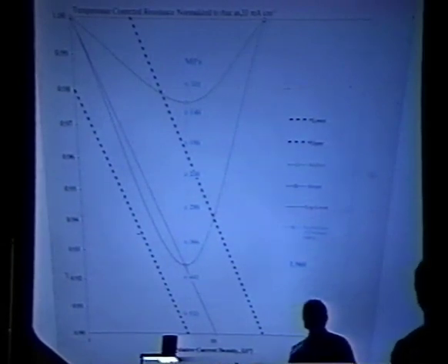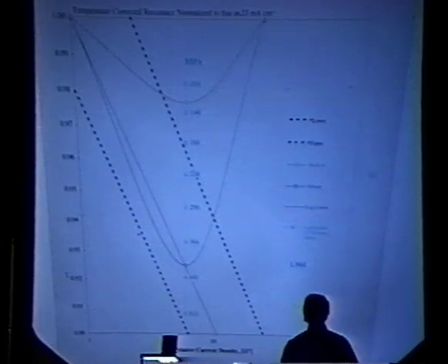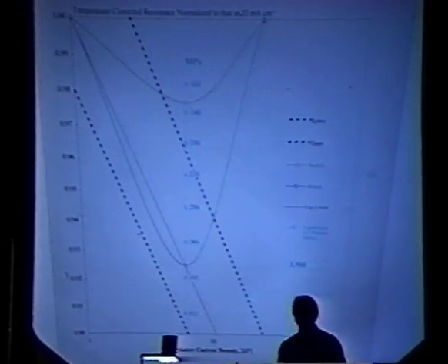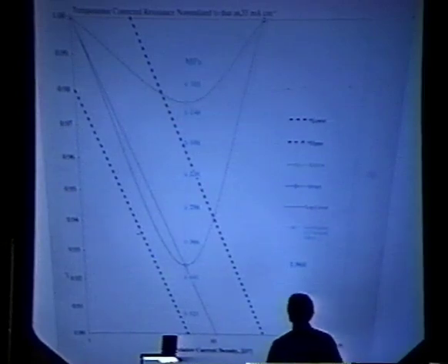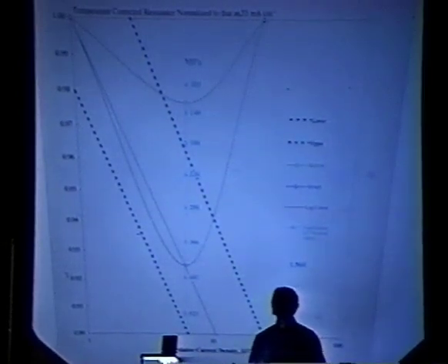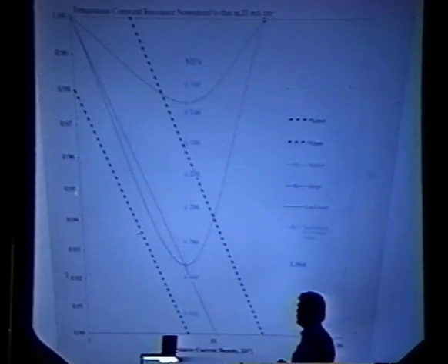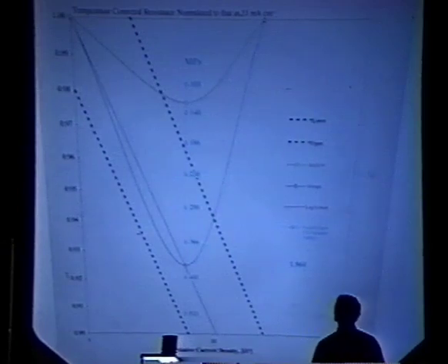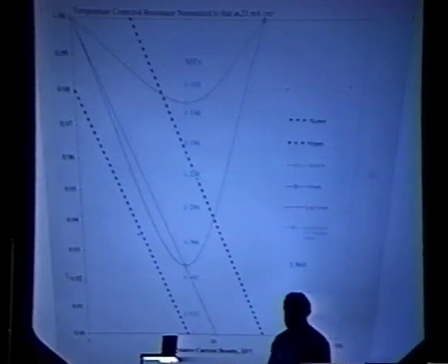In both mode A and mode B, we have obtained the correct electrochemical conditions, but the mechanical character of the palladium is insufficient, just too weak to tolerate the high loadings that we need to obtain the resistance ratios that we're looking for and the chemical potential of deuterium in the lattice that we're seeking.